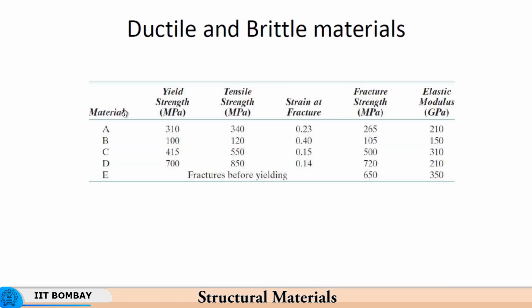So, this is high strength steel, whereas here the strength is low, although the Young's modulus is the same at 210 GPa. C is a material in between, it has got 310 GPa as the Young's modulus and an intermediate strength. So, the ratio of tensile strength to the yield strength is an indicator of the relative strain in uniform deformation. So, if the difference is very high, then you will get a good strain under uniform deformation.